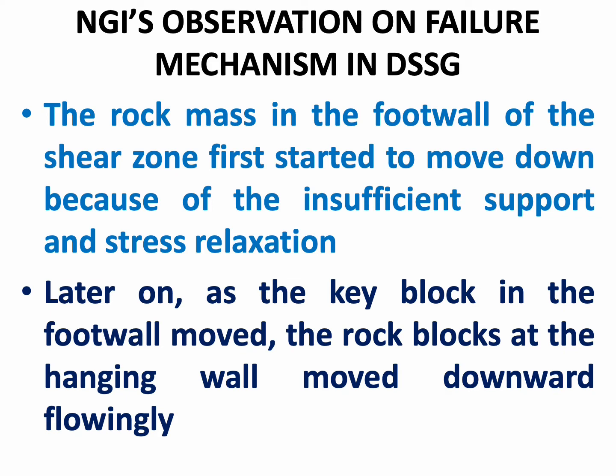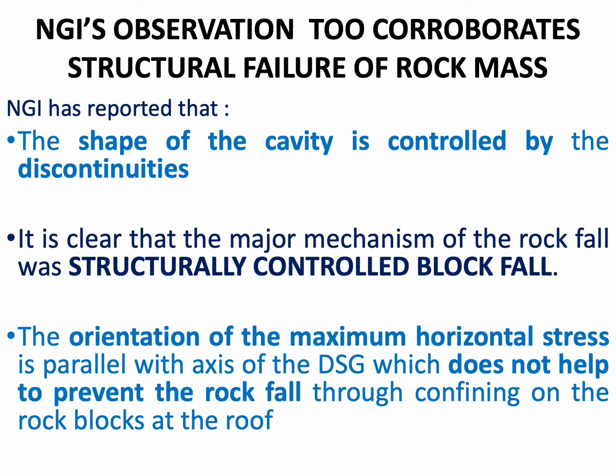NGI's observation of failure mechanism is that rock mass in the footwall of the shear zone first started to move down because of the insufficient support and stress relaxation. Later on, as the key block in the footwall moved, the rock blocks at the hanging wall moved downward flowingly. This is what NGI concludes. NGI's observation too corroborates structural failure of the rock mass. NGI has reported that the shape of the cavity is controlled by the discontinuities. It is clear that the major mechanism of the rockfall was structurally controlled blockfall.